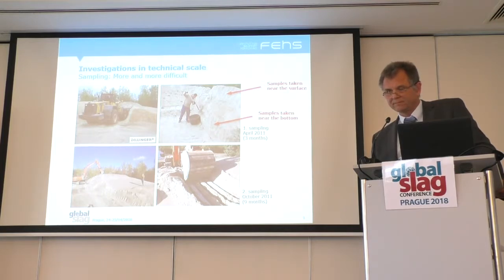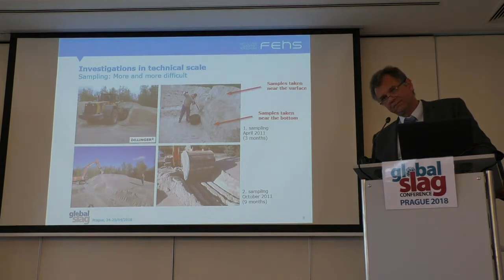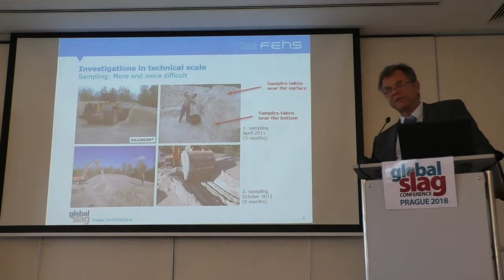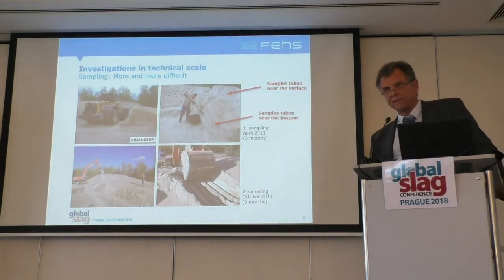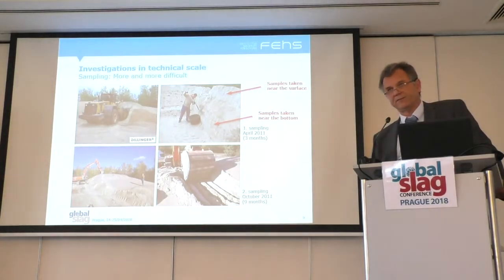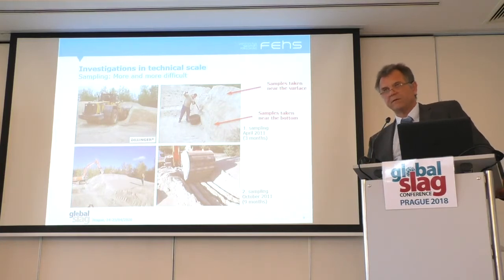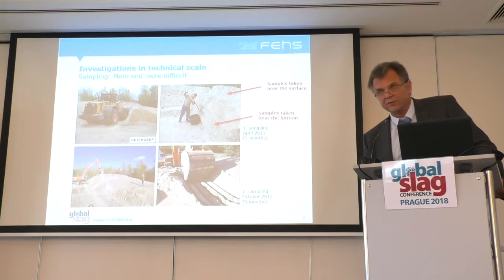So from your research, you mentioned that even if you store it longer, more than 2 years, and the sample is from the bottom, the strength didn't decrease as time goes. We found it several times in lab scale, in these technical scale tests, and we found it also in practice. We had once a customer who was interested to use a 1 million ton GBS stockpile stored since 1945, unused. And he came to us with samples. We investigated it with the same procedure, and we found the same results.